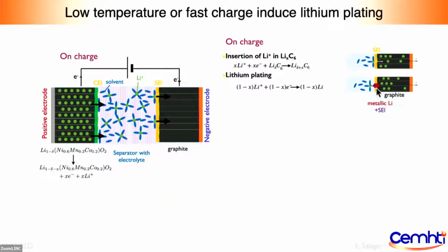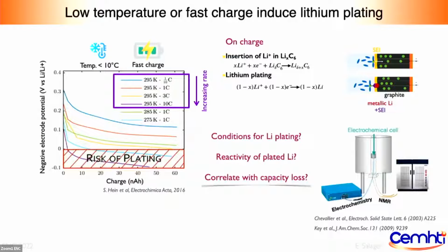And this has been identified as the main source of capacity fade. So right now, how the constructors are avoiding this problem is by measuring in a battery, adding a third electrode to measure the potential of the negative electrode, and then they identify when the potential is below that of the lithium plus lithium zero couple, and they devise charging protocols that avoid this region.